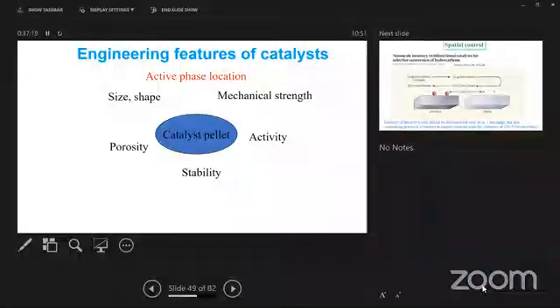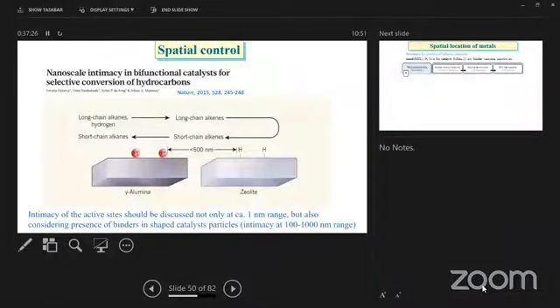The most interesting things are starting now. It's about the influence of the metal. For a very long time, there was some sort of an assumption that the closer the acid sites to the metal sites, the better it is. That was called the concept of site proximity or intimacy of active sites. And this is something which is used as an important concept in oil refining, especially in hydrocracking and in hydroisomerization, where you have the metal function and you have the acid function. So the idea is that they should be put close to each other, the metals and then the acid sites.